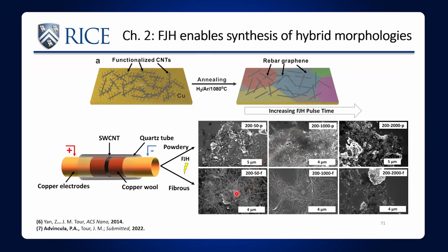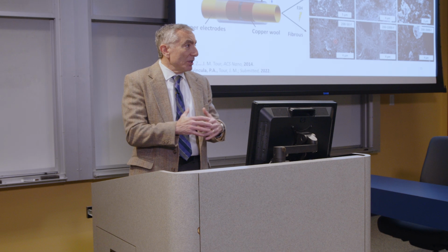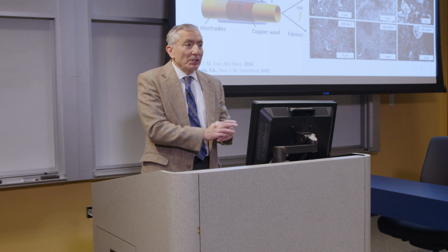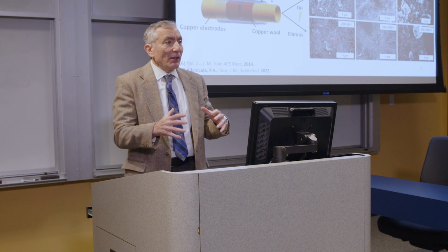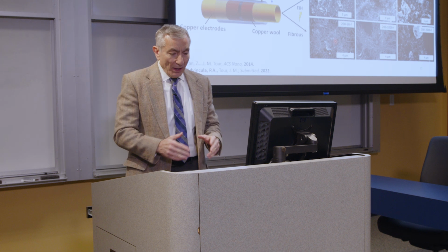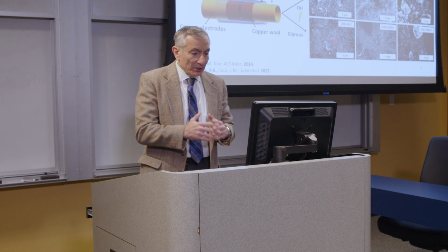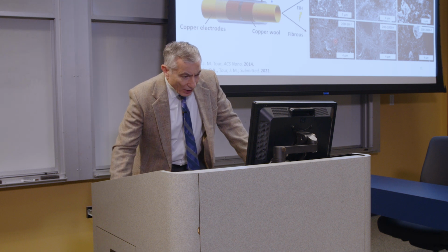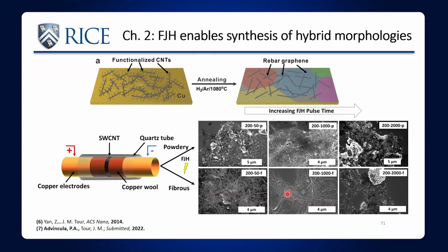So you have this melding of graphene and carbon nanotubes. So it gives you an enhanced material. You're taking two different nanomaterials and growing them together and hooking them together. And the temperatures are high enough where you get this carbon-carbon fusing together. And so you can see these regions where you have these strings of graphene, these strings of nanotubes, and then these graphene domains between them.